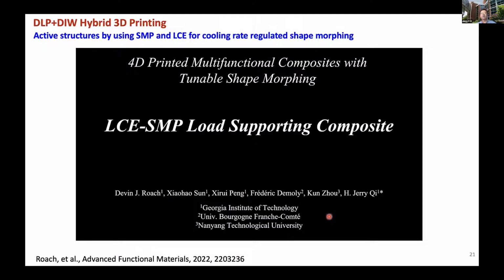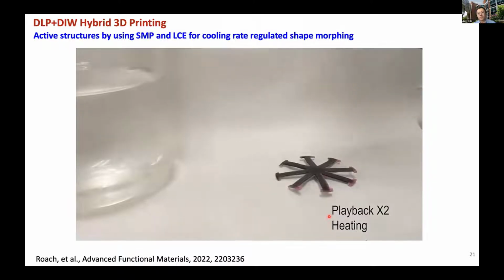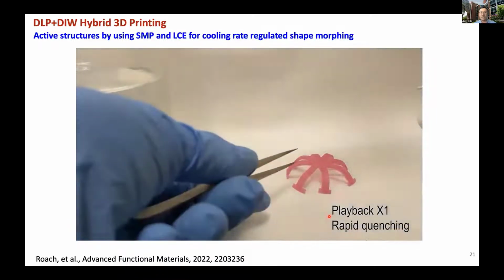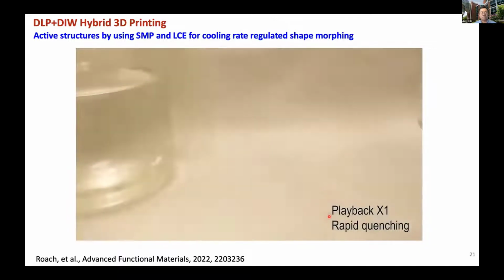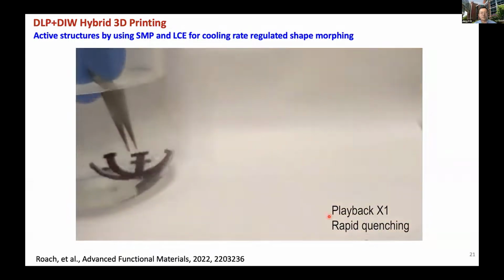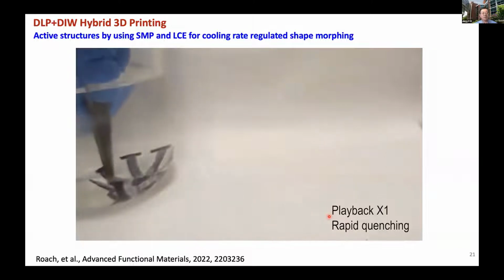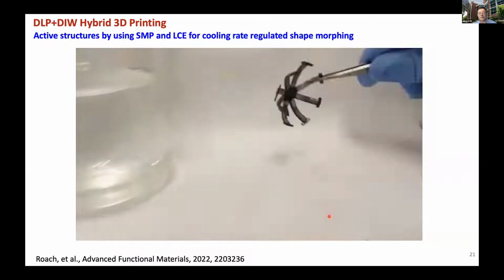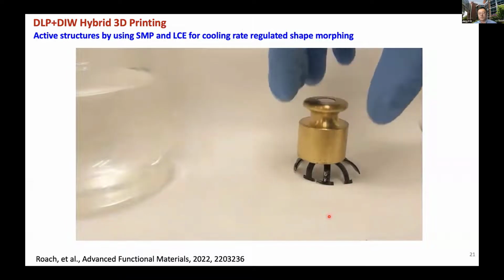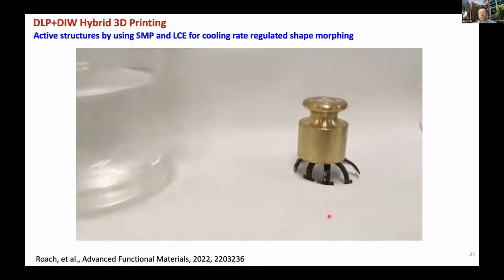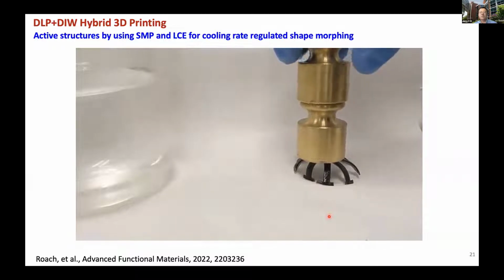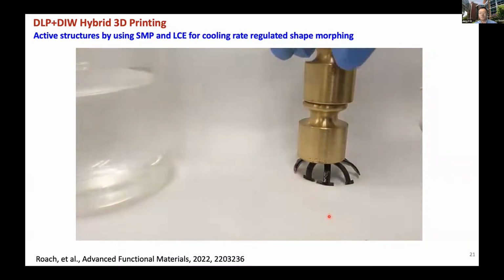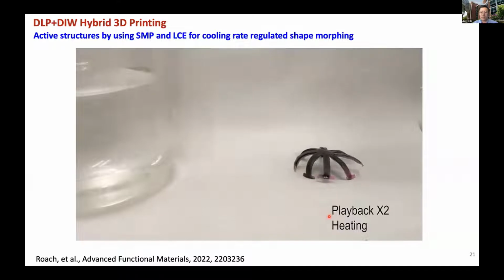And like I said before, at a low temperature the material is actually a shape memory polymer. Low temperature in glassy state is very stiff, so this shape can actually support the load. In this case, we heat it up, and then we move it to ice water. You can see here the cooling is not that fast, so you see a little bit of recovery, but after you take it out, it becomes pretty stiff. In this case, we can put 1 or 2 kilograms of weight. This kind of structure can still support that weight. And when you heat it up, it just comes back.